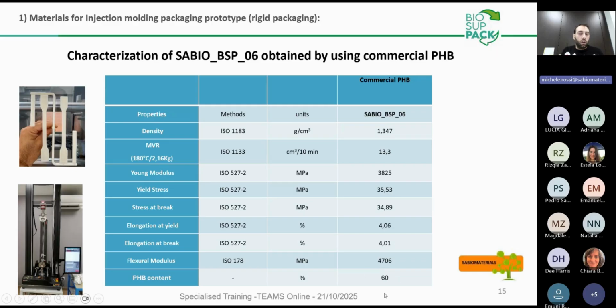The PHB content is around 60%, but we also saw potential in other very interesting data. This means the stress at break is very high, close to 35 megapascal, and also the elongation. We take into consideration that the elongation is typically not very good because it's only around 4%. But regarding the final article, a beer display that does not have a stress of elongation during its life, this parameter for us is not taken too much into consideration. So 4% is enough. What is important is the rigidity and the strength of the final material. So in that case, the numbers obtained are very good.